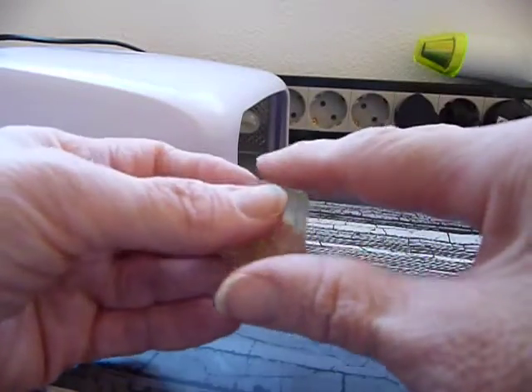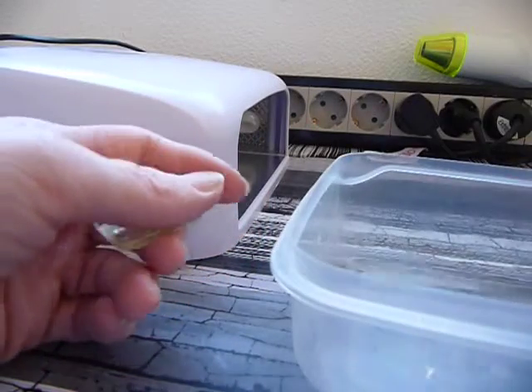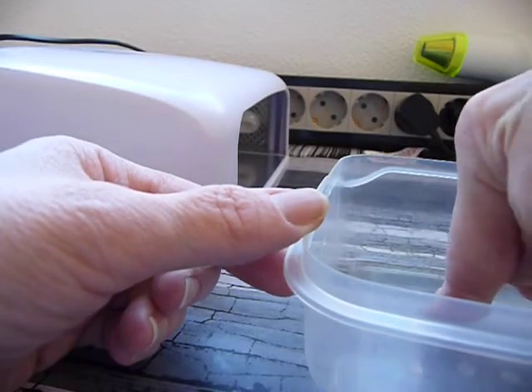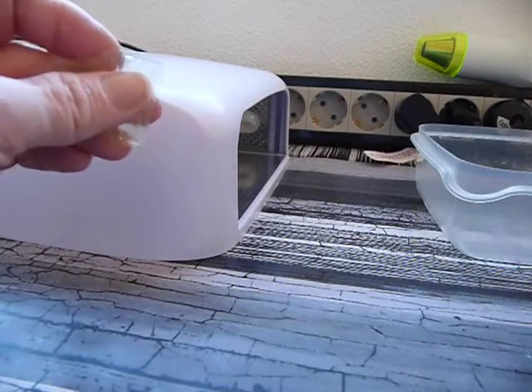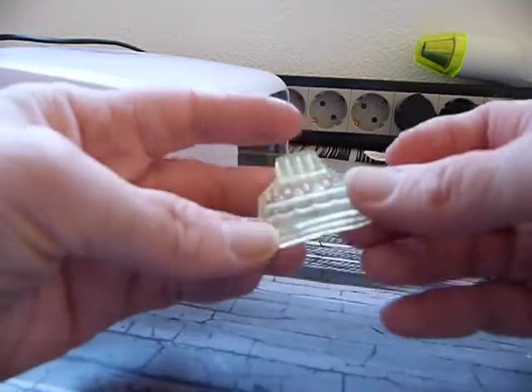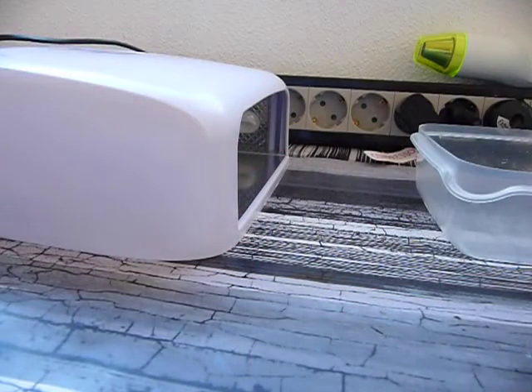Once you've taken it out and washed it, put it into a plastic tray with just a tiny amount of water to cover the stamp. Cure it again for about six minutes, allow it to dry, and you end up with a stamp. Things can go well and they can go badly - it just depends on the timing.